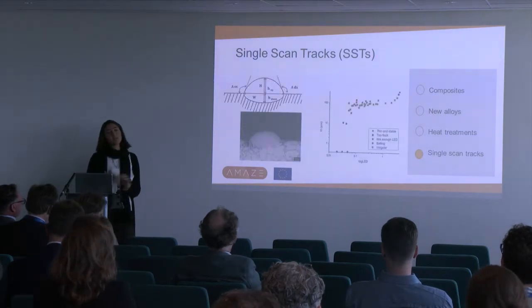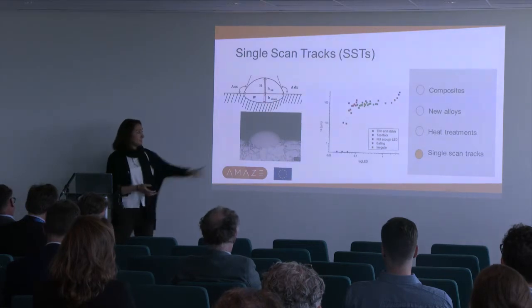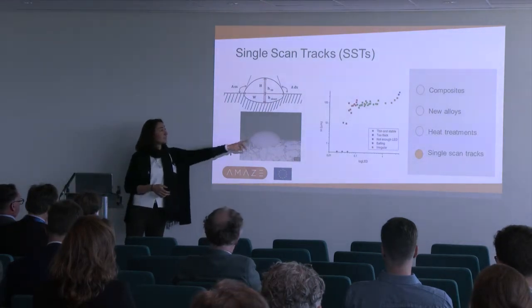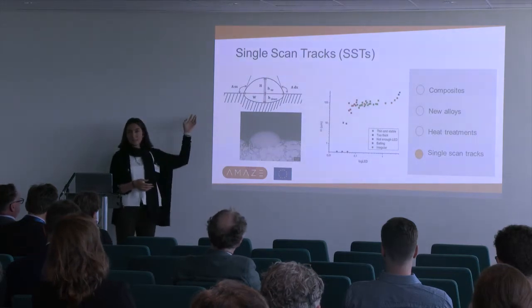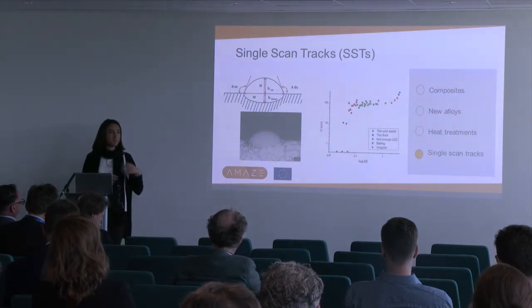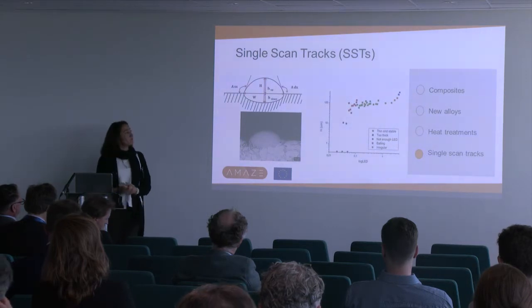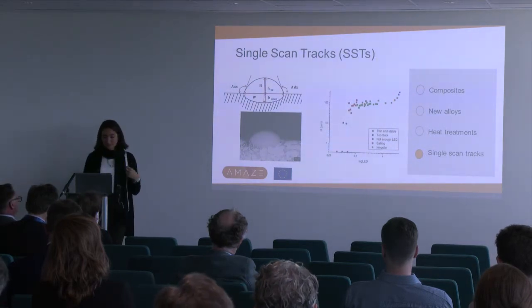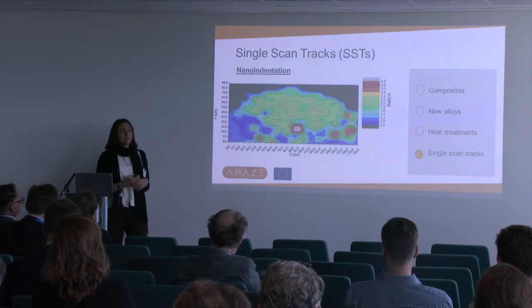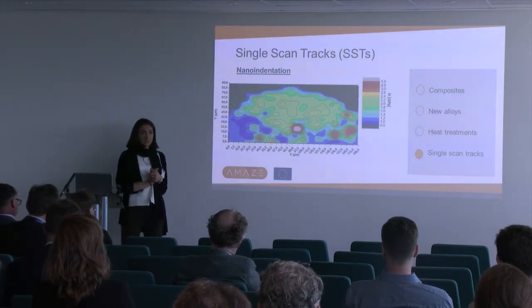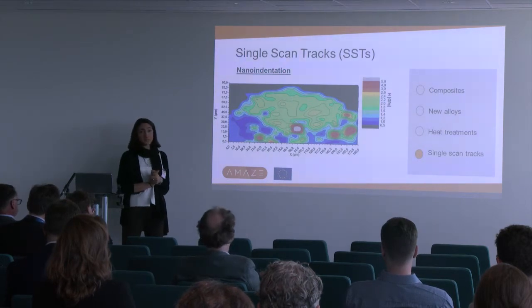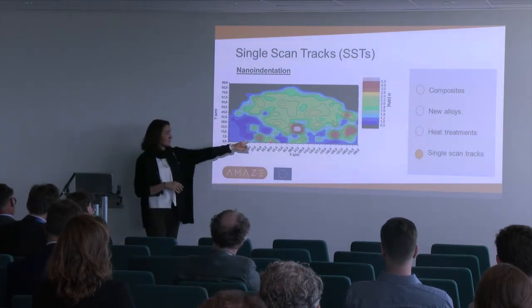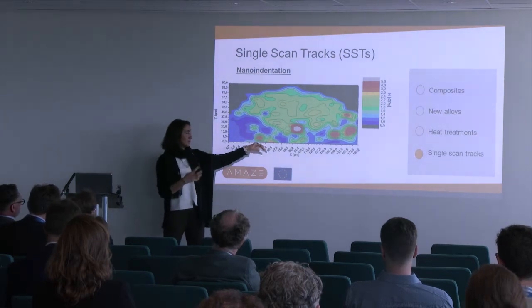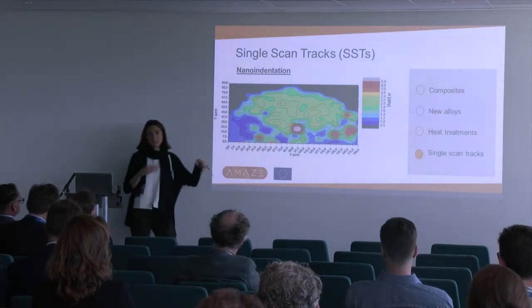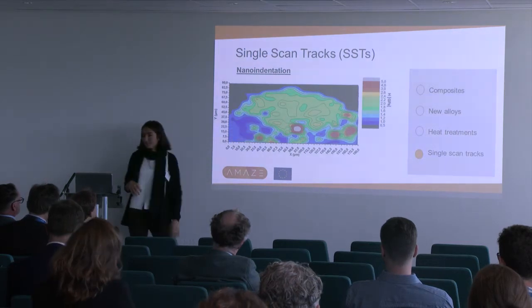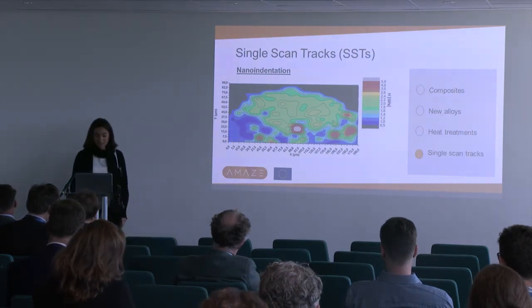Then we cut all the single scans. This is an example: we have the cast area, the single scan, and we measured all these geometrical features. So we have some interesting trends that can explain which phenomena take place. The last thing we did was to perform some nano indentation analysis on this single scan track. Here we can see the cast part, with some really red, strong, hard parts that are the precipitates in the cast part, while the green area is, in this case, the single scan track.